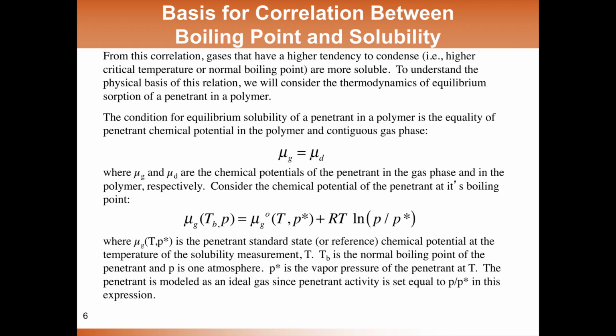It begins from the point of view that the condition for thermodynamic equilibrium is that the chemical potential of a penetrant in a gas phase is equal to that in the polymer or dissolved phase. And it is this equality of chemical potential that is the definition of thermodynamic partitioning between two phases.